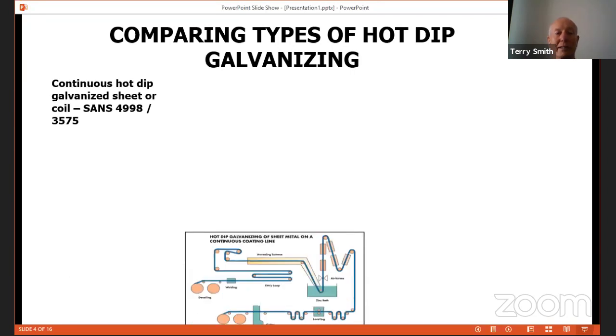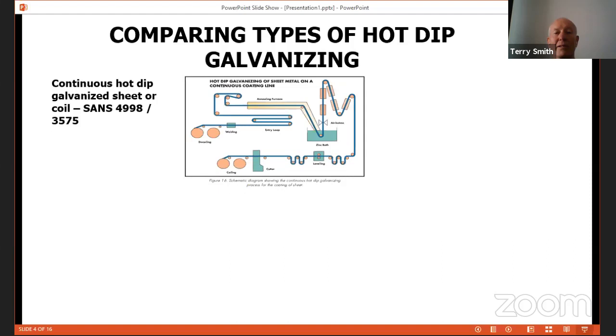Comparing types of hot-dip galvanizing, you have continuous hot-dip galvanized sheet to that standard. This is the process. Items are decoiled and go through a welding process, looping, and then into an annealing furnace, which is heated to about 900 degrees C, runs down into the zinc bath at about 100 to 140 meters a minute, through these gas or air knives, which mechanically wipe the coating to the different coating grades that are available.